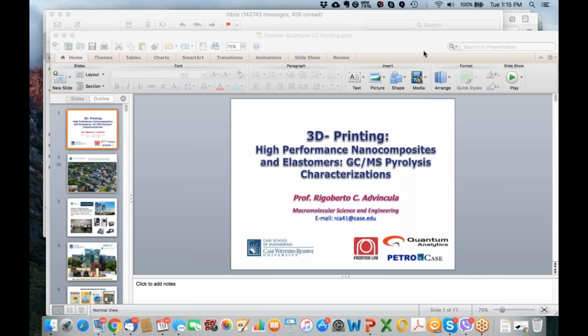Other kinds of technology, one is based on a filament technique. You can think of this as taking the sample in a quartz tube and placing it essentially inside the filament of an incandescent light bulb, in a platinum filament, so to speak. So that analysis is initiated by turning the switch on and energizing the filament, and that filament then heats the sample. In that case, you're heating it up in a transient way in which the filament then passes its energy through the quartz tube and to the sample.